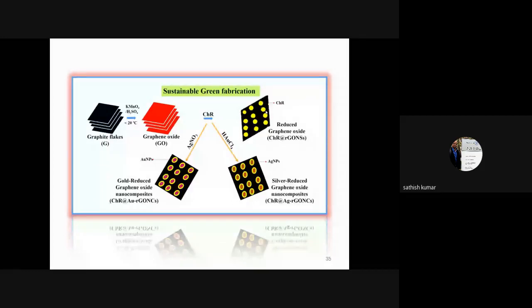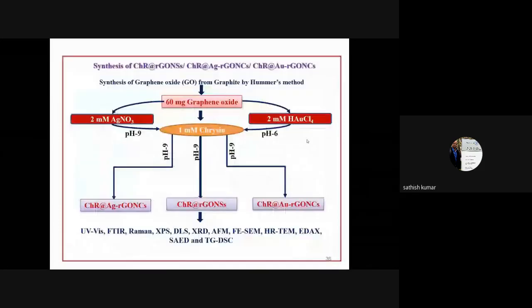And after successfully synthesizing the reduced graphene oxide, we got an idea to synthesize both reduced graphene oxide and the metal ion in a composite formation. So here we have used both graphene oxide and silver nitrate for the synthesis of silver nanoparticle decorated graphene oxide, and for the gold, we have used chloroauric acid and graphene oxide to synthesize gold nanoparticle decorated reduced graphene oxide nanocomposites. In both cases, we have used chrysin, and you can see the chrysin is capped on the nanoparticle surface. So this is the synthesis protocol.